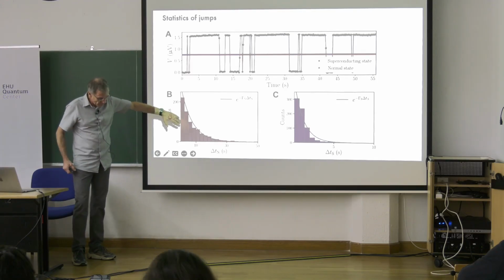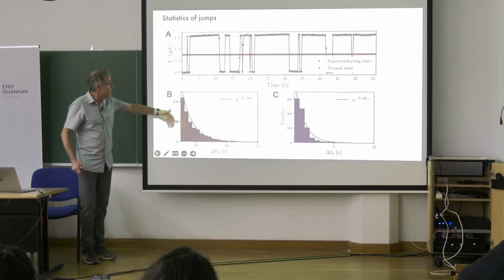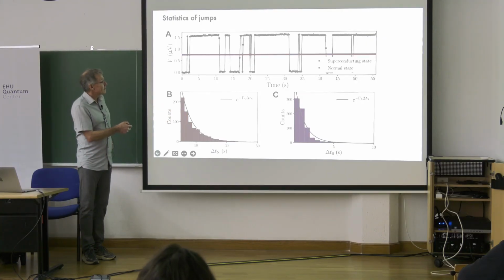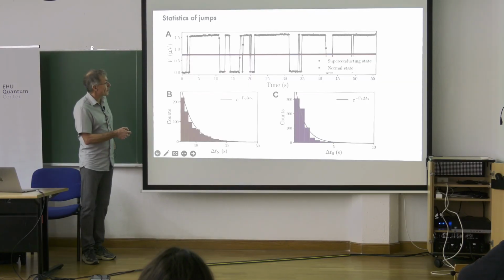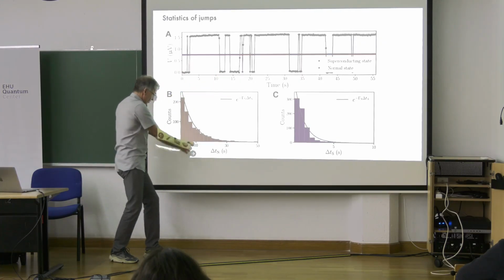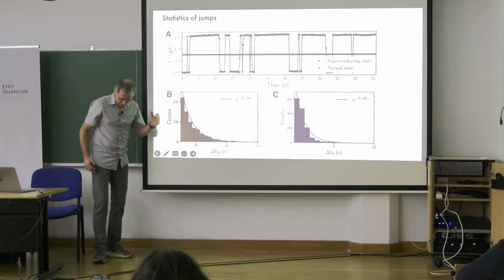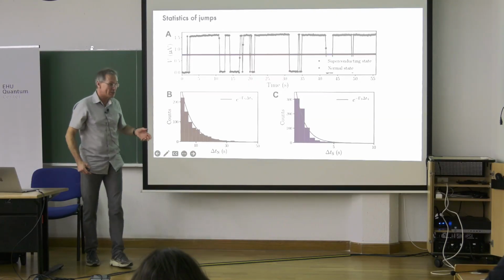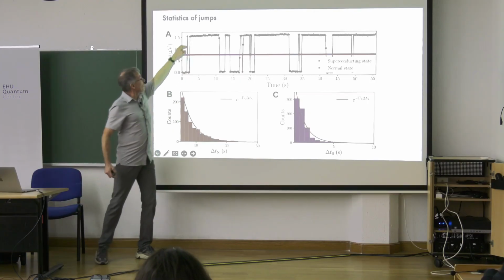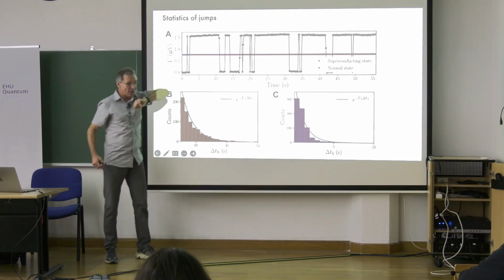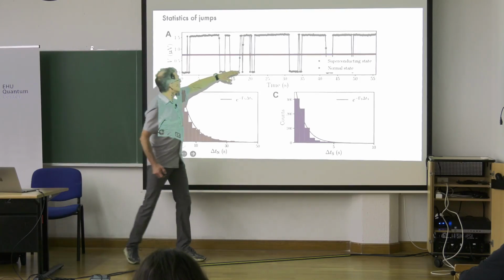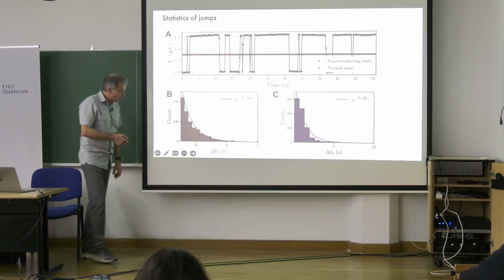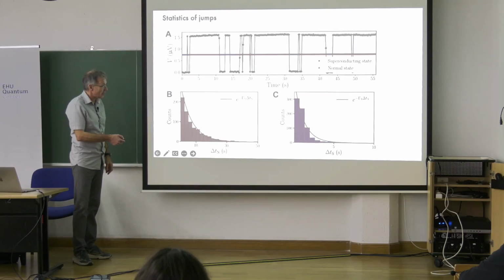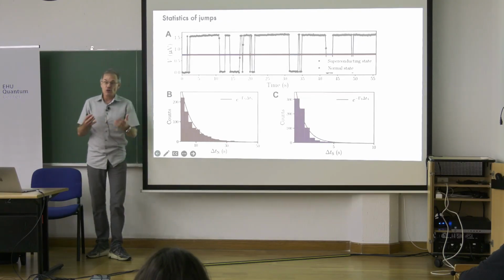Then they can put a histogram, put counts, of what is the lifetime of the normal state and the superconducting state. You run the experiment many times and look at how often it can stay in this state for this amount of time, and in this state for this. And it all fits pretty well to exponential behavior, which is a typical property of decay physics.